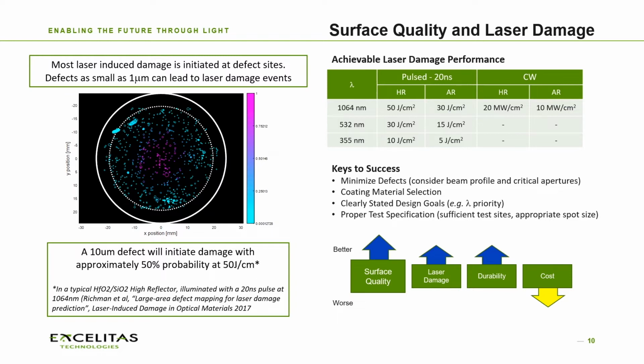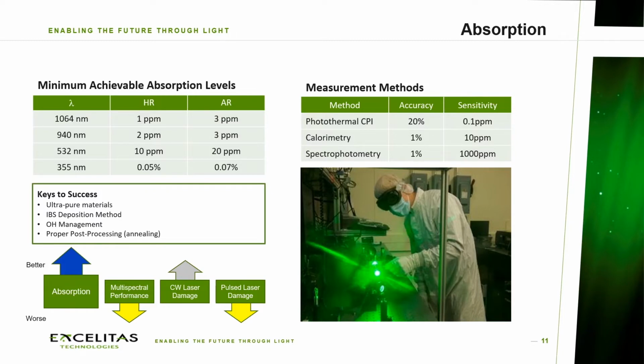The next specification that we need to be paying attention to, particularly for CW applications, is absorption. Now, absorption can come from many different sources. There's lots of different mechanisms, but luckily it can be pretty low at 1064. If we're making optics out of very high quality materials and using the best processes, we can actually get into the single-digit ppm level of absorption on a fairly regular basis. In fact, as low as 1 ppm.